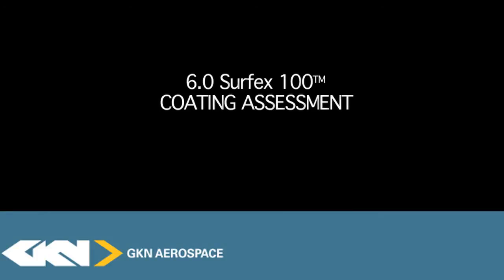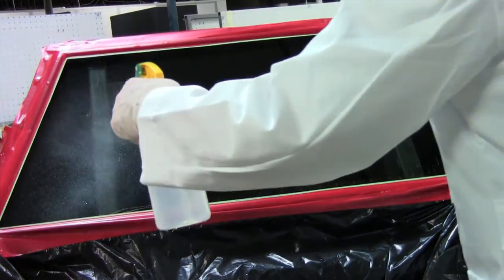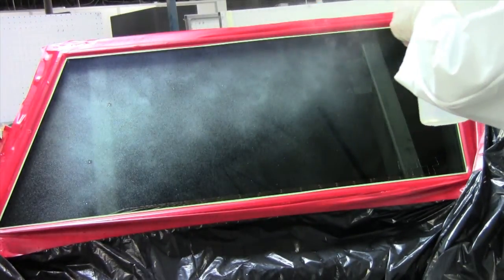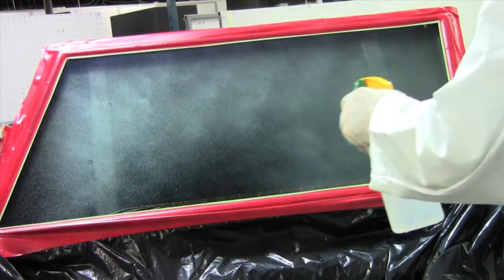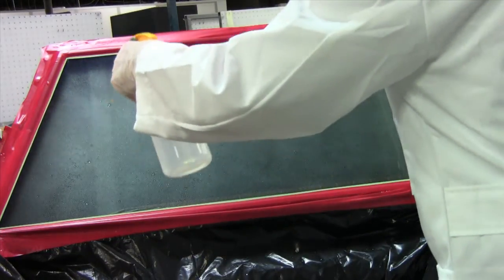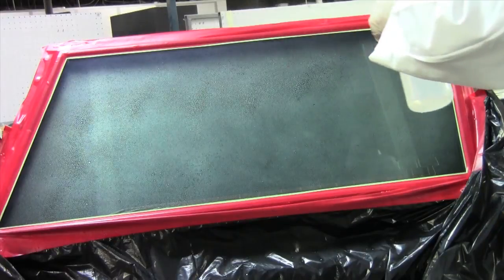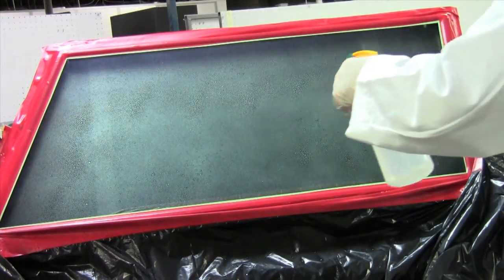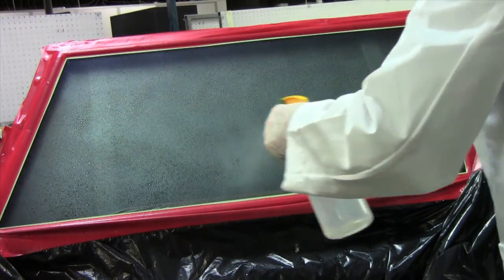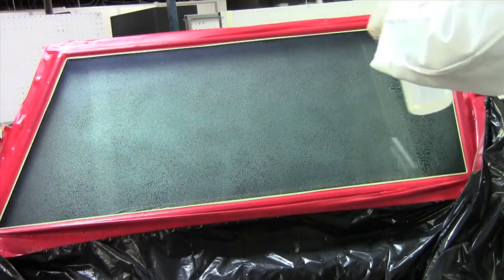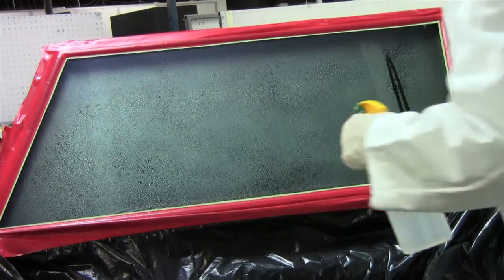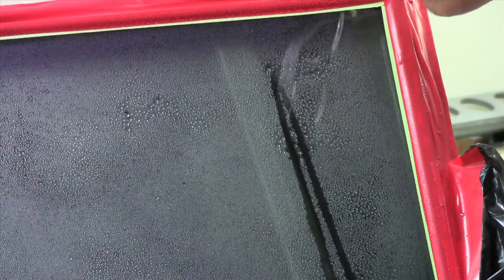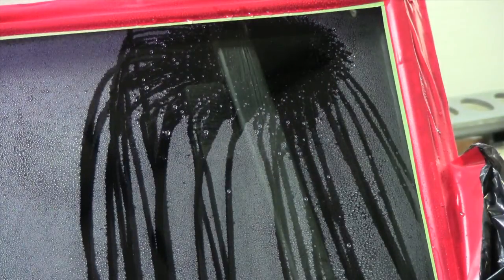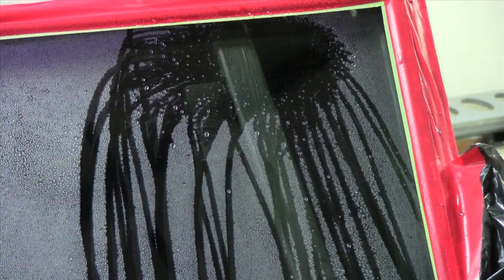Surfex 100 Coating Assessment. This method is a simple viewing of the glass surface after wetting the surface with deionized water from a spray nozzle. Refer to Appendix B for photographic comparison. Clean the windshield with isopropanol and wipe dry with wipes. Coating A, as new coating. All the spray water remains beaded up in very small droplets. Tracks running down the windshield will be completely clear of any water in the tracks themselves. This coating is very water repellent.